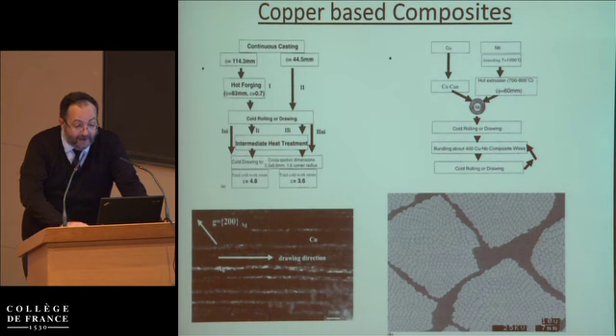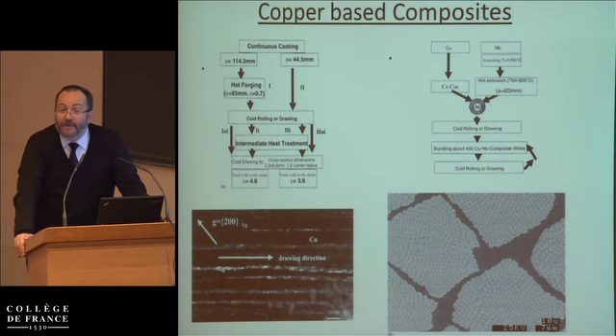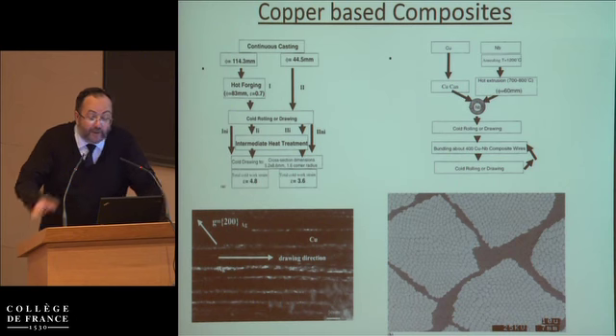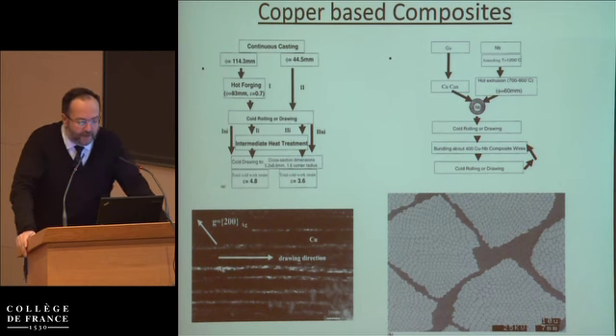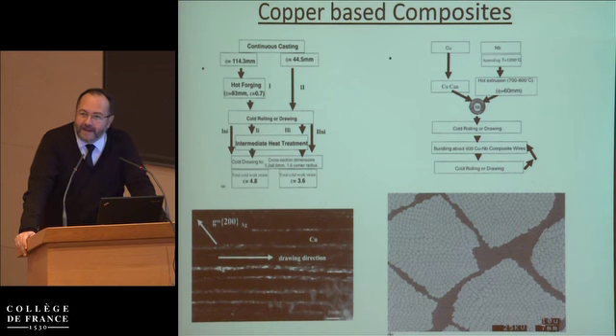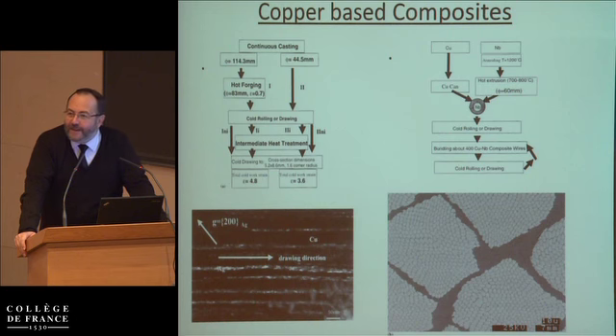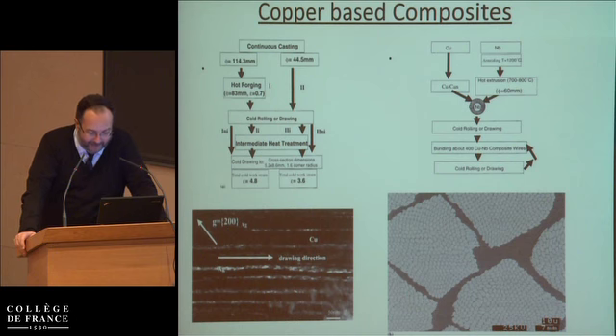Now, one way of dealing with that is to make a composite of composites, and we'll see this example in a number of cases in natural materials again. And this composite is using, for instance, a copper niobium multi-filament structure, which will be extruded. When it's extruded, you just take the extruded fibers and you put them together again, and again, and again, and you are going to have a multi-architectured structure when you go down from the nanometric scale up to the microns, or up to the millimeter, which is the size of the final cable that you try to obtain.